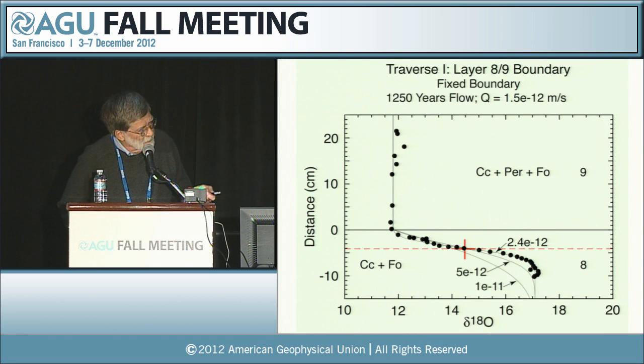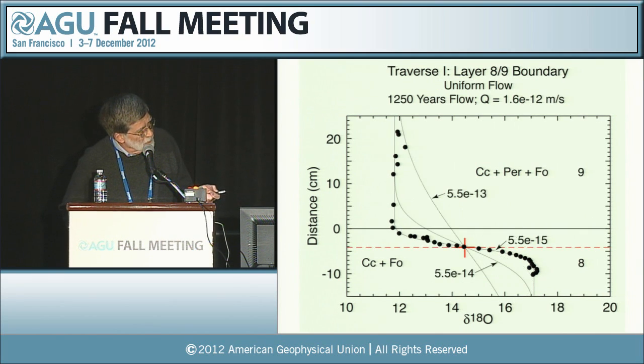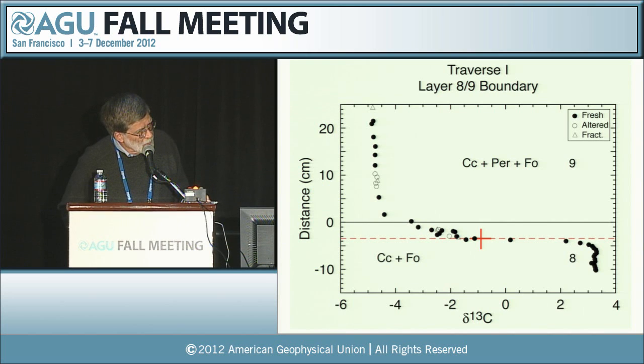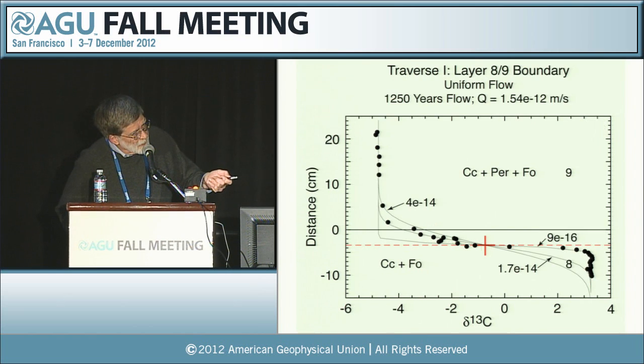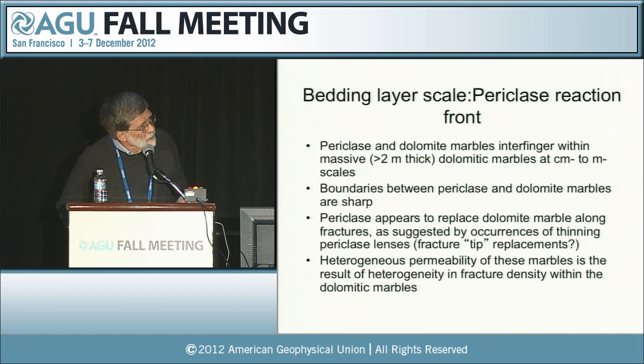The actual value depends a bit on the kind of model one picks. If you pick a fixed boundary model, you get values of the diffusion dispersion coefficient much lower, 10 to the minus 12. If you use a uniform flow model, you get something even lower. So these are much lower diffusion dispersion coefficients at the smaller layer boundary scale. Okay, and here's the carbon profile. Something very similar: constant homogeneous compositions within the layers, and a steep coherent gradient at the layer boundary that's very slightly displaced from it. And again, you get very low values of the dispersion coefficient.